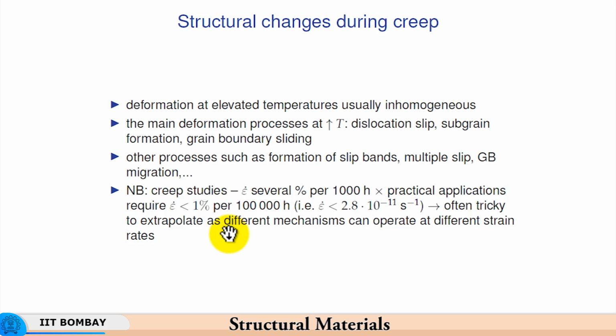Now, the amount of creep strain, as I told earlier, is an extremely small strain developing over a large period of time. So we have a strain of less than 1% per 1 lakh hours. Basically 2.8 into 10 to the power minus 11 seconds inverse is the order of magnitude of strain rate that can be tolerated. I am not saying expected, because expected is 0, but you cannot avoid creep strains at high temperatures and stresses. Therefore, the strain rate has to be maintained.